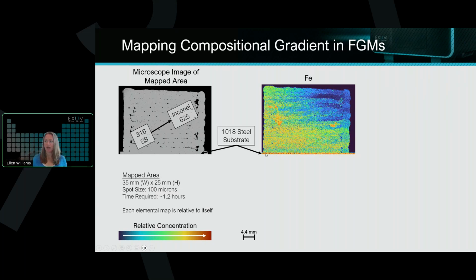And so you can see in this case, we've got the highest concentration of iron where we hit just a little bit of that substrate, and then we see a relatively high concentration of iron in the bottom left corner, transitioning to a lower concentration up in the top right. And that makes sense. We know that iron is a major constituent of 316L stainless steel, and it's a minor or lower concentration in the Inconel. Every single one of these pixels that you see on one of these images is a 100 micron laser spot with a full mass spectrum of data behind it.